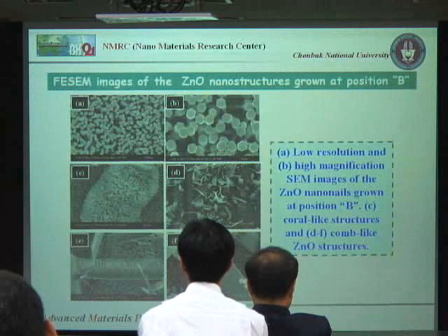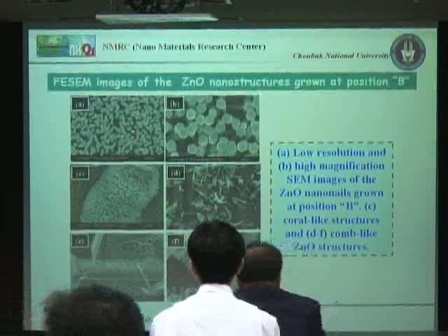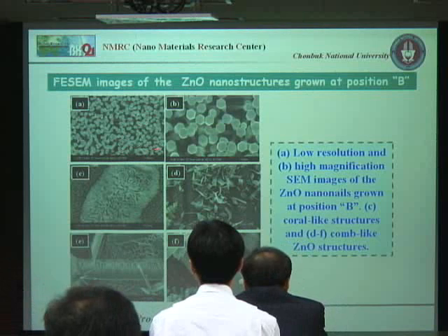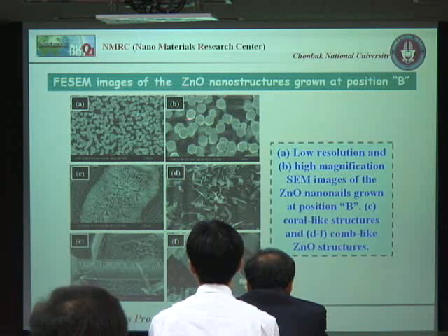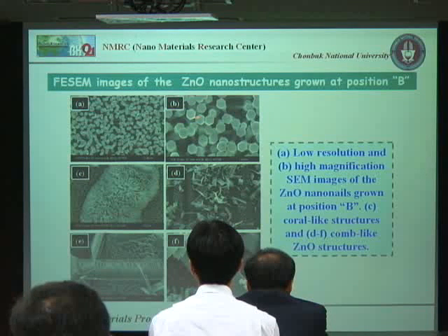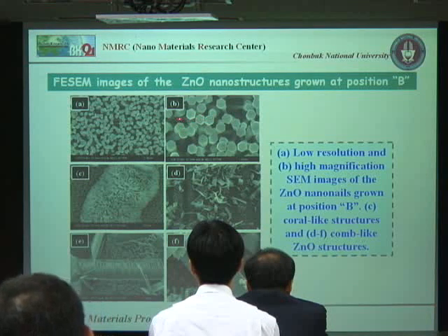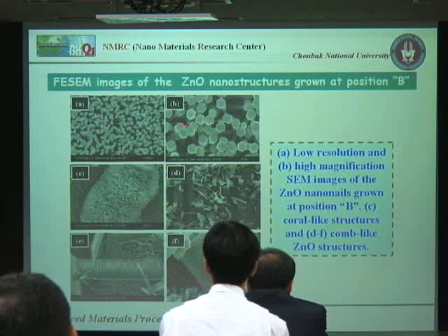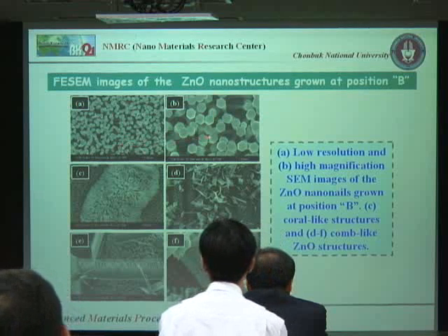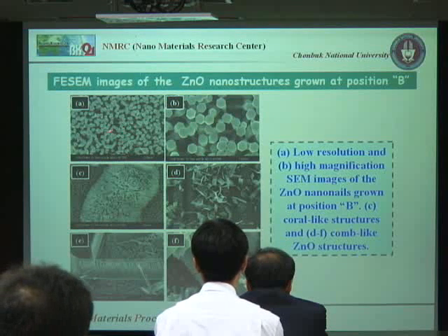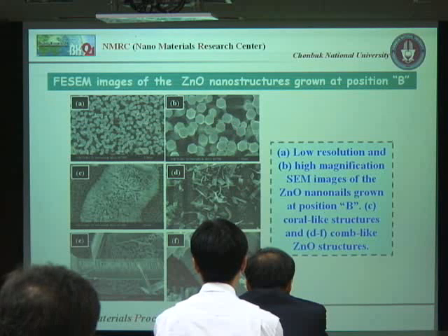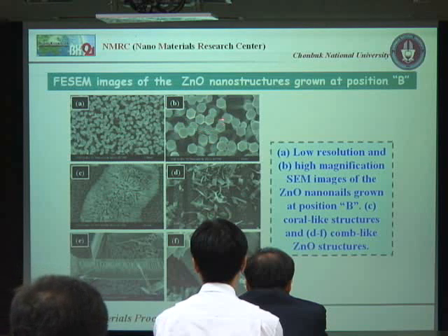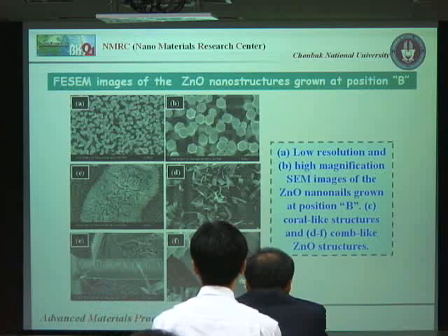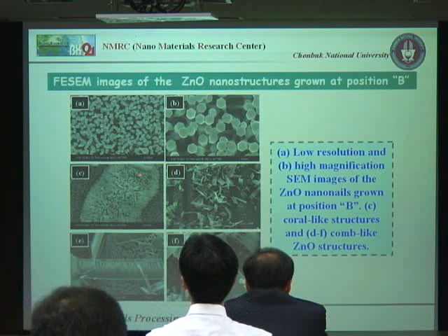From position B, we got some more interesting morphologies. We got aligned zinc oxide nanonails on the whole substrate surface. We can clearly see that the upper portion of these nanonails shows a perfect hexagonal facet, which is because of the crystal structure of zinc oxide. And these nanonails are grown in very high density, as we can see from the low magnification images. In addition to the aligned nanonails, we also got some coral-like structures on the upper portion, made by these nanonails. Maybe thousands of nanonails are together and they made these coral-like structures.